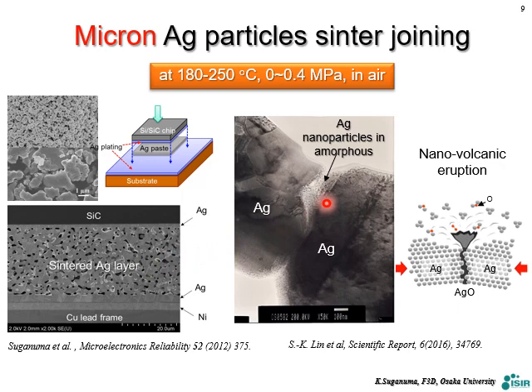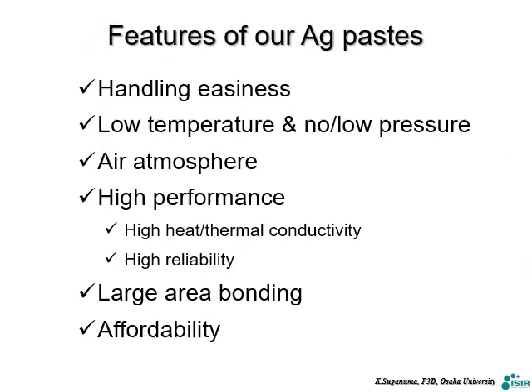Finally, we got a conclusion. This mechanism is the so-called nanovolcanic reaction. Silver is an interesting material. Silver absorbs oxygen along grain boundaries, and oxygen in the grain boundary forms silver oxide liquid. So this becomes liquid, and under some stress, this liquid comes onto the surface, forming an amorphous layer first. Immediately it turns into pure silver nanomaterials and promotes sintering. This is the sintering mechanism at low temperature. Because of this specific reaction mechanism, we can get good bonding.